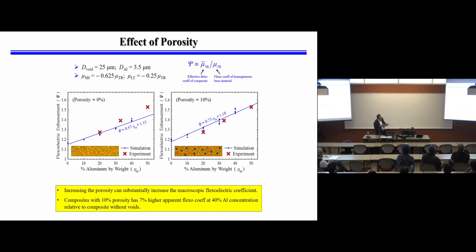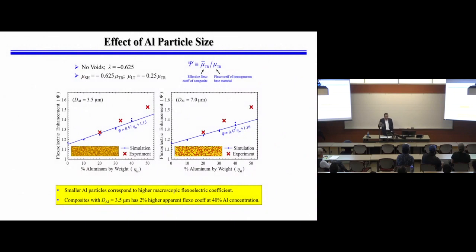We talked about the amount of aluminum particles, the solids. How about porosity? This one has no pores, no voids, and this is about 10% voids. Obviously, the voids allow you to significantly enhance the output. Without voids, the enhancement in the electrical output is less. So when you have voids, you also match the experiment. That's relative to the homogeneous, pure material, in terms of ratios of how much output you can get. So voids are important as well. Any type of heterogeneity helps with the phenomenon.